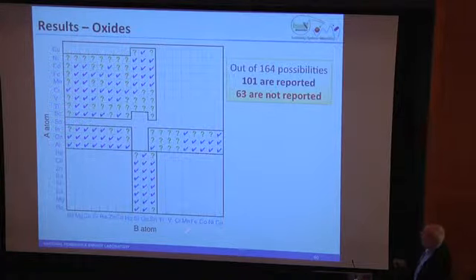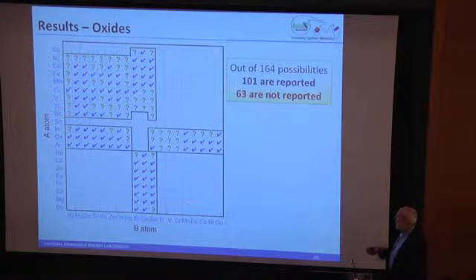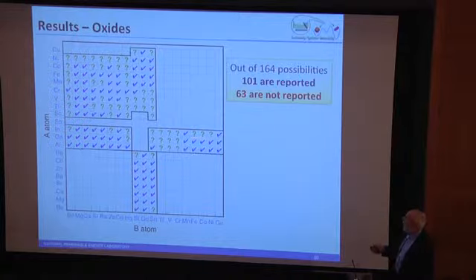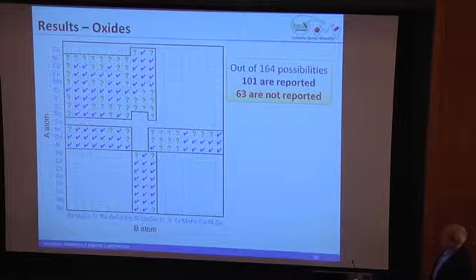If you look at all the possible spinels, and this is oxides, you have the A atom, the B atom. Things with check marks are things that have been made. Things with the open squares here are things we don't even expect to be able to be made. And things with question marks are things that actually ought to be thermodynamically stable but have never been made. So the first point is there's a lot of them. This is far more than what we expected.